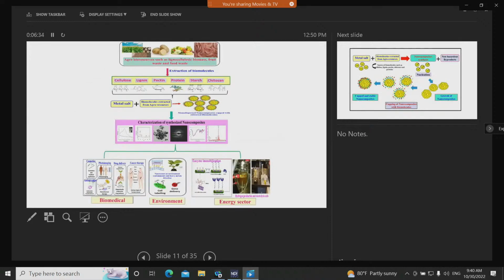Those are usually followed. Our research mainly focuses on the extraction of biomolecules, such as cellulose, lignin, pectin, protein, starch, and chitosan. Those are extracted using the lignocellulosic biomass that is obtained from agro-bioresources, fruit waste, and food waste. So when these extracted biomolecules come in contact with the metal salts, they form stable monodisperse composites that are capped with the biomolecules. And further, they are confirmed by using various characterization techniques such as XRD, EDX, HRTEM, and other characterization tools to confirm the particle size, shape, and morphology.